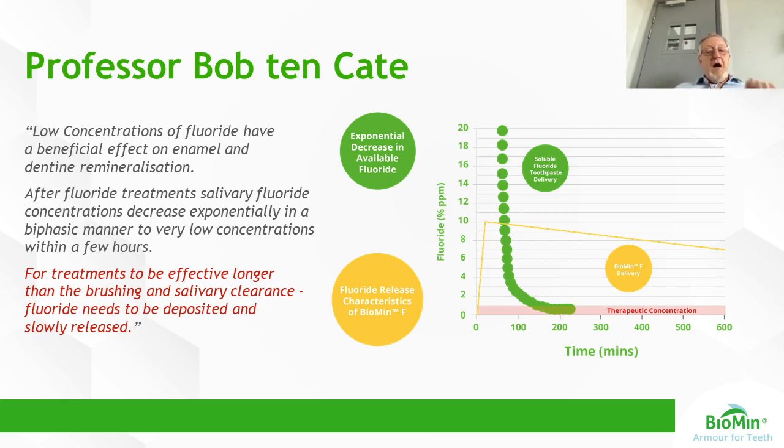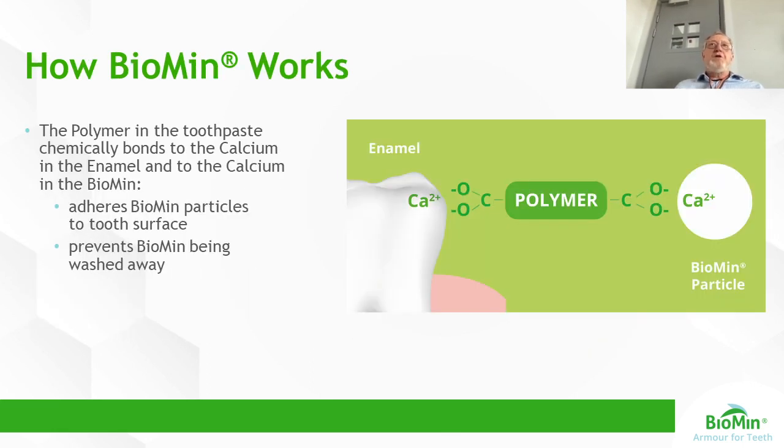He said this in a number of his review articles: for treatments to be effective longer than the brushing and salivary clearance time, fluoride needs to be deposited and slowly released. And this is what we do with the BioMin F glass in the toothpaste. Essentially, the glass particles stick to the tooth surface, and they also stick, incidentally, to the soft tissues in the mouth.